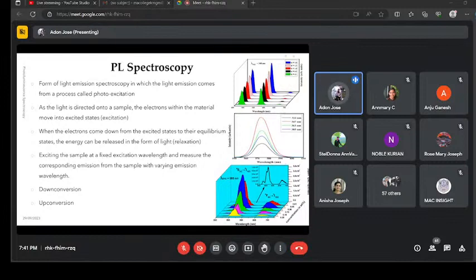We have discussed several non-radiative relaxation processes present in a luminescent material: vibrational relaxation, non-radiative de-excitation, internal conversion, and intersystem crossing. Based on all these non-radiative relaxations, the electrons relax to the equilibrium state. Then after that, it will emit light. That means it goes through a radiative transition to the lowest ground state. So exciting the sample at a fixed excitation wavelength and measuring the corresponding emission from the sample with varying emission wavelength is the process we go through whenever we are recording a photoluminescence spectrum.